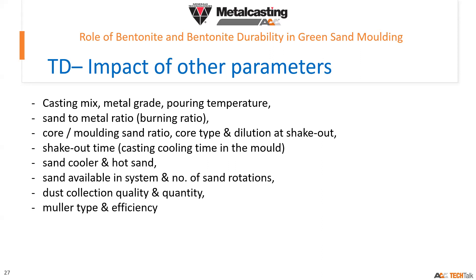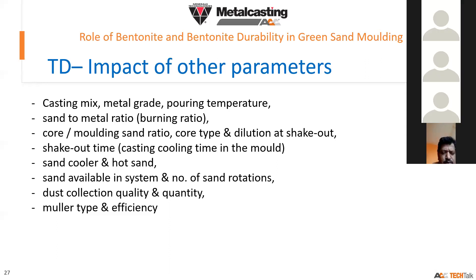Such cores getting into the system will also affect results. For example, a cold-box core or shell core will cause very high dilution, whereas a CO2 core or no-bake core will cause very low dilution. Similarly, shake-out time matters — based upon casting cooling time and how long we keep the casting in the mold, we decide the burnout performance and burnout properties.